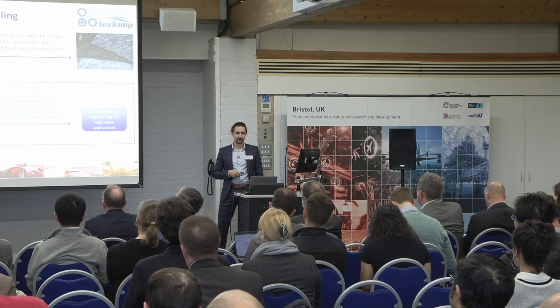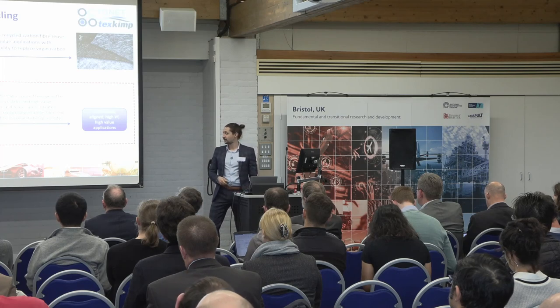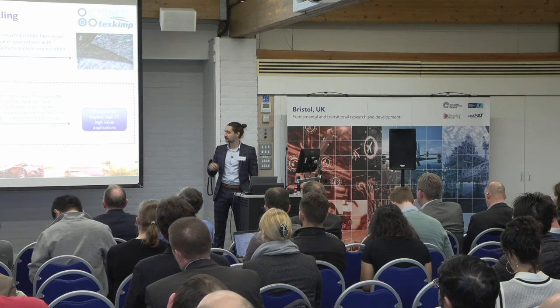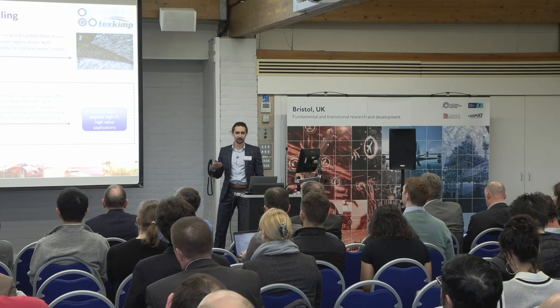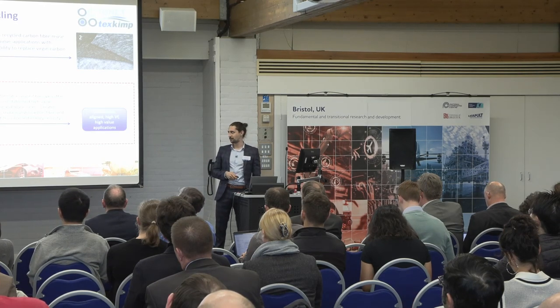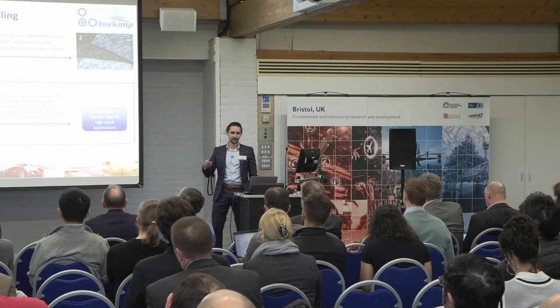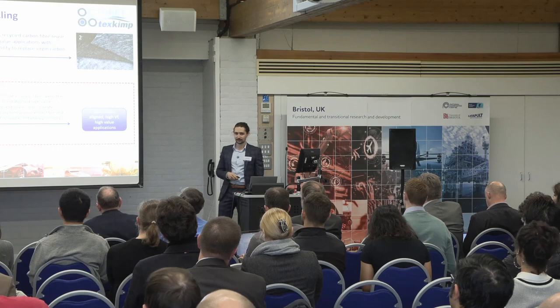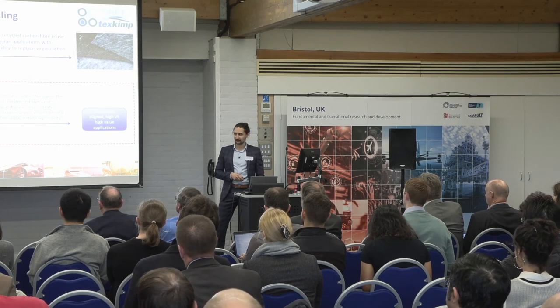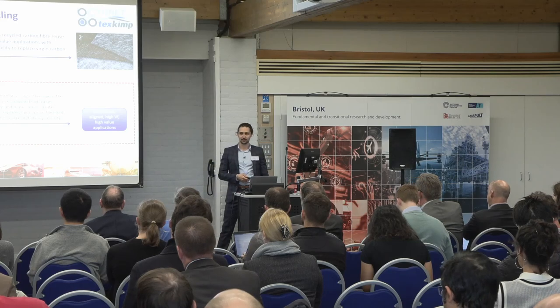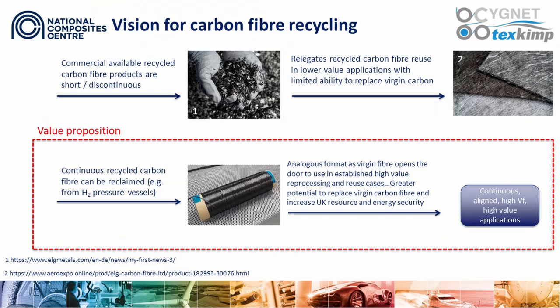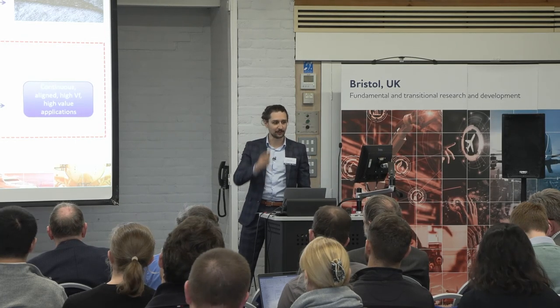The value proposition here is that there are some end-of-life products, such as filament wound products or tanks, which do actually have continuous or semi-continuous tows still in them. So if we recycle these in an appropriate way, we can in theory extract those continuous carbon fibers, which may be a better drop-in solution to virgin materials in some cases, and therefore have a greater potential to actually replace virgin materials and ensure our UK resource and energy security. One thing I want to highlight here is that most of the waste will probably still be in this discontinuous format anyway, so we still obviously need high-value solutions for this discontinuous material, like what we heard about Linea and what I think Phil will talk about later.